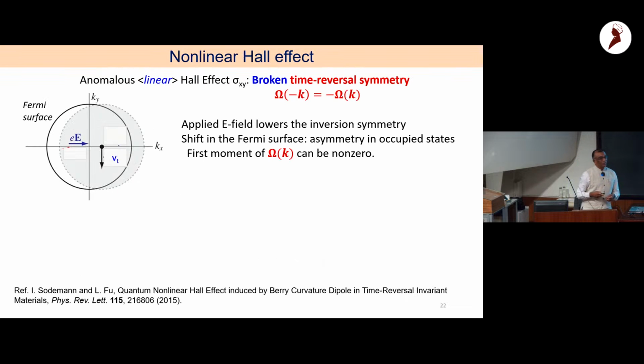Okay? So there are some very interesting developments recently. It's called the nonlinear Hall effect. Basically, there is the anomalous linear Hall effect, which is governed by the conductivity I defined, and that requires you to have broken time reversal symmetry. But what was shown in this work is if you apply an electric field in the x direction, the Fermi surface in the system displaces to the right or to the left, depending on the direction of the field. And when that happens, the applied electric field lowers the inversion symmetry and shifts the Fermi surface, creating asymmetry in the occupied states. So although the Berry curvature may be symmetric, you create asymmetry in the states which are going to contribute to your integral.